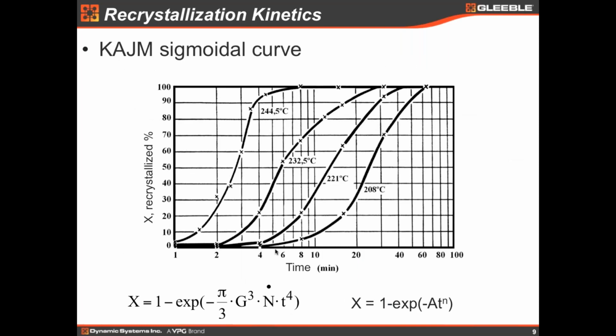Regarding the kinetics, how fast recrystallization happens, it follows a sigmoidal curve, or S curve, or the Kolmogorov, Avrami, Johnson, and Mehl equation. These are the researchers who in the past derived and modeled this equation. Kolmogorov, the Russian researcher, was the first one, followed by Avrami and Johnson and Mehl. Johnson and Mehl made the most didactic derivation of the sigmoidal curve, and this is the equation due to Johnson and Mehl. Basically, you have the fraction recrystallized here and the time. In the beginning it's very slow and then the velocity increases, and at some point, when the growing grains start to touch each other, the speed slowly decreases.